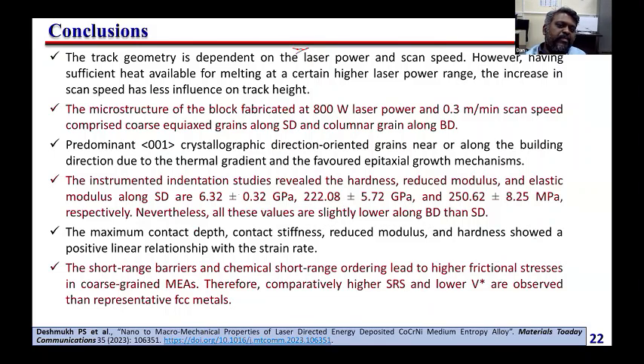So from this deposition, we could optimize the laser power and scan speed for this sample, and we understood that there is a predominantly 001 texture in the building direction.